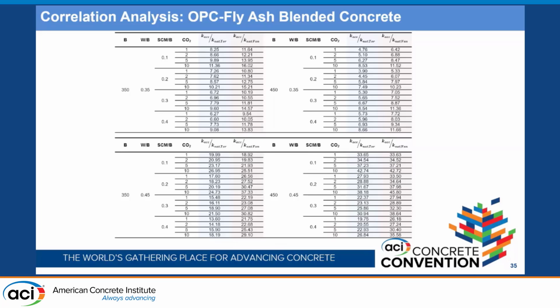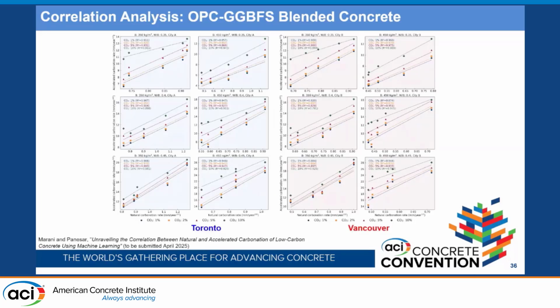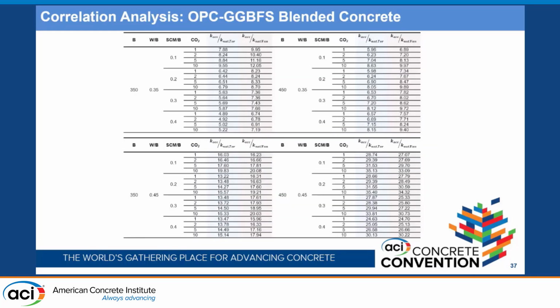So these are the results for the fly ash. We have the same results for the slag, again for the two cities of Toronto and Vancouver. And again, we can establish very good linear correlation indexes and correlations in general for the mixtures between the accelerated and natural carbonation. And again, we have the same type of results here for the case of slag concrete.